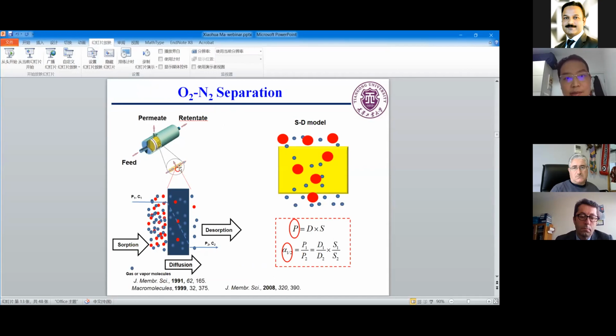Let's go to one single hollow fiber: the gas dissolves at the upstream and diffuses in the membrane to the downstream for desorption. In general, for this kind of non-porous membrane, the principle is solution-diffusion. There are two parameters. The first is the permeability of the dense membrane. The higher the permeability, the more membrane area you save. The other is the selectivity. The higher the selectivity, the purer the product you get, so you can also save pump energy.